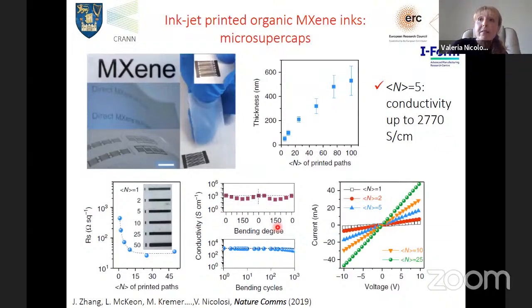And it was really resistant to bending. We could bend several times up to 180 degrees, and the conductivity was not really affected. And here, over several hundreds and thousands of bending cycles, the conductivity was always stable.